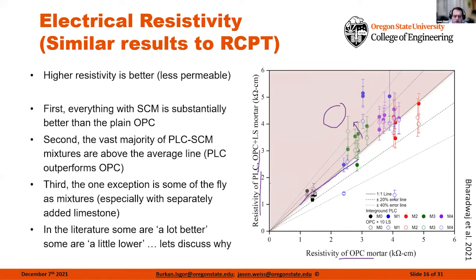But I think the other thing to really have as a takeaway here, these are your systems that don't have SCMs in them. And you'll notice where your resistivities are. They're kind of in this 1.5 kilo ohm centimeter range. However, if we start to increase the SCMs in the system, we now notice that our resistivity doubles or triples. And by doing this, we've made it 2 or 3 times harder for chloride ions to get through the system.